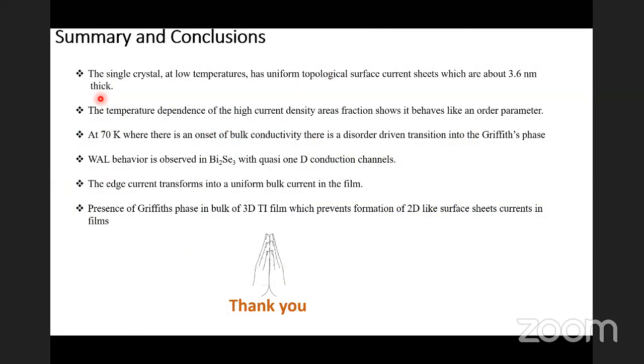So I come to the summary. From our study of imaging of these single crystals at low temperatures, it has uniform topological 2D-like surface sheets, which you can see, which are about 3.6 nanometers thick. With temperature, these high current density area fractions behave like an order parameter. It shows a sudden decrease at 70 Kelvin, where there is an onset of bulk conductivity, and the system breaks up into patches, where there is local order surrounded by normal electrons.